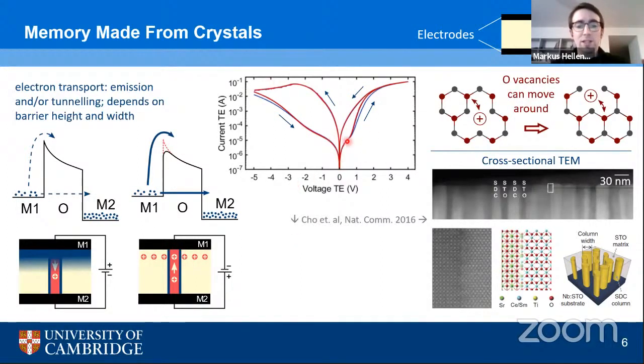And in the other direction, again, first, the oxygen vacancies are still accumulated, so we get a fairly high current. But at the same time, we're pushing them away from the interface so that the barrier becomes higher again. And when going back to 0, now the current is lower than it was before. So we have 4 branches in this current versus voltage curve, and we can identify this with a certain resistance of the device.